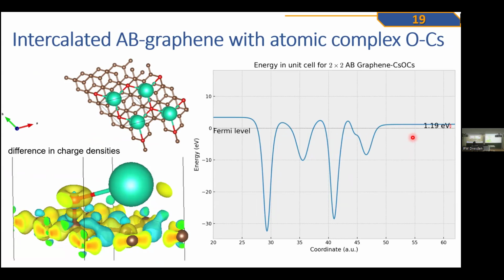intercalated defect-free AB graphene with an oxygen cesium atomic complex on the surface. In addition to the lowest value of the work function of 1.19 electron volts, we can see that the top cesium atom is relatively close to the oxygen atom, and the oxygen atom is close to the carbon one. That is in contrast to the previous cases when the oxygen cesium complexes typically form van der Waals bonds. In this case, a covalent bond is possible.